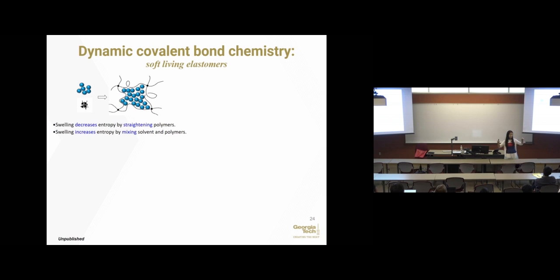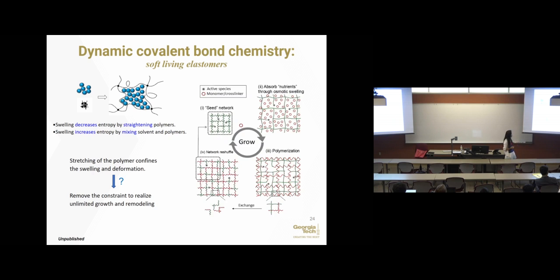The elastic energy is very high, and the network doesn't like to be stretched. To a certain extent, that defines your ultimate swelling amount, right? And the idea we were thinking about is whether we can get rid of this constraint, change the covalent bond on the main chain into dynamic bond. So now, you can open up the bond and incorporate more monomers, for example, to release this stress. Then you can keep swelling and reacting, so you can continuously grow. So that is the idea.